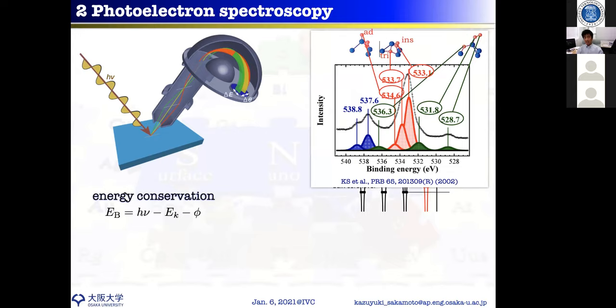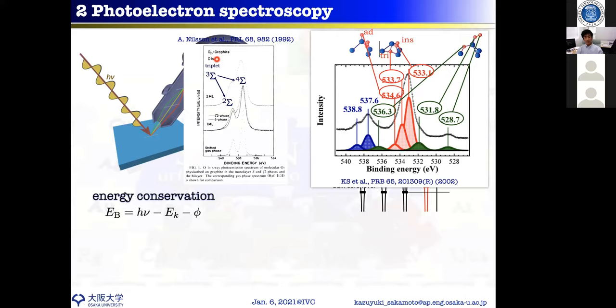The green peaks decrease in intensity over time — they represent a metastable species. By measuring the core level, you can get information about how molecules and atomic species adsorb at the surface. There are also two additional peaks from physisorbed oxygen molecules. Although there is only one adsorption configuration, you observe two peaks due to the final state effect: oxygen is paramagnetic with parallel spins, and exciting different electrons leads to different final states with different energies.